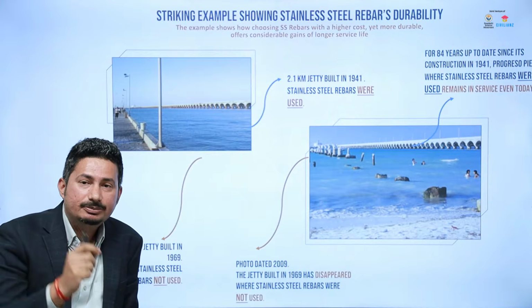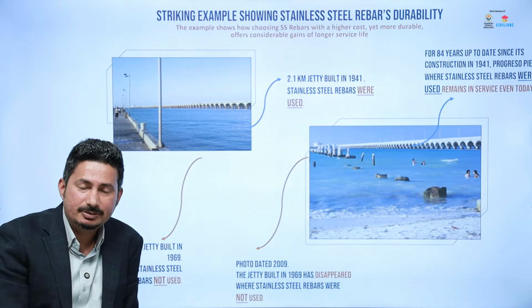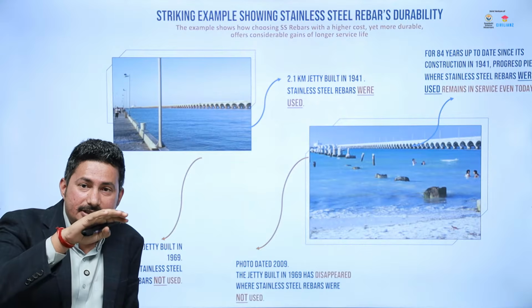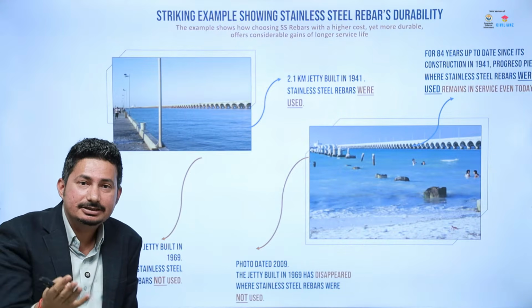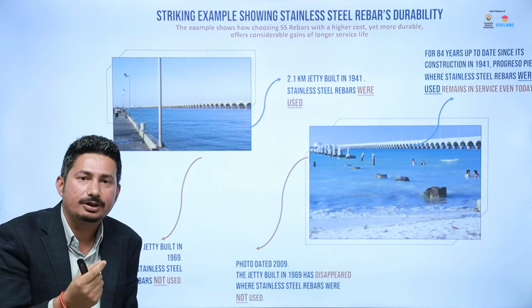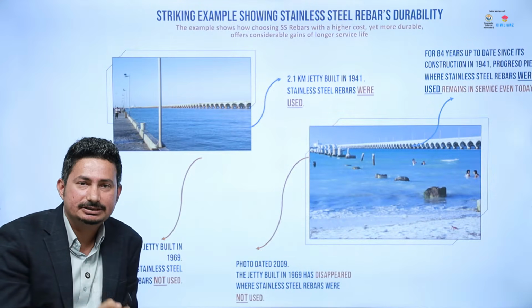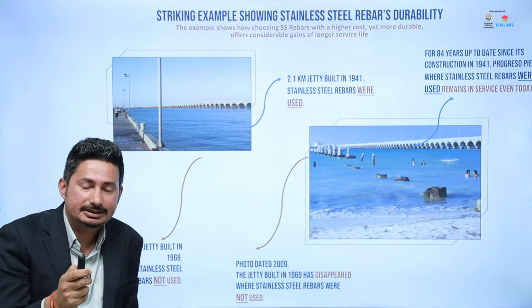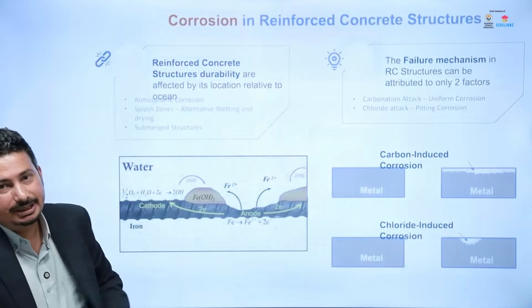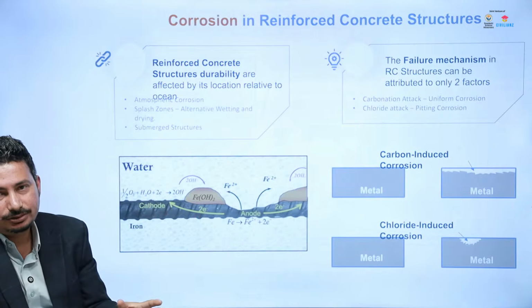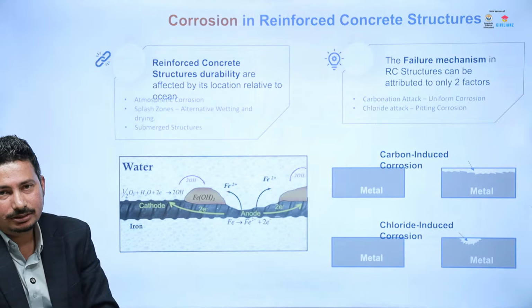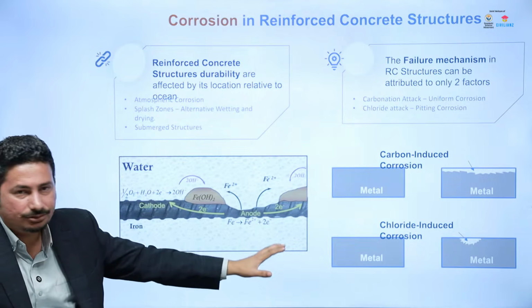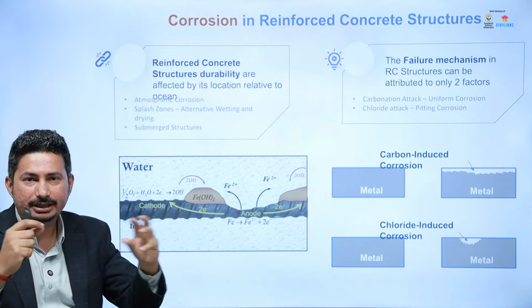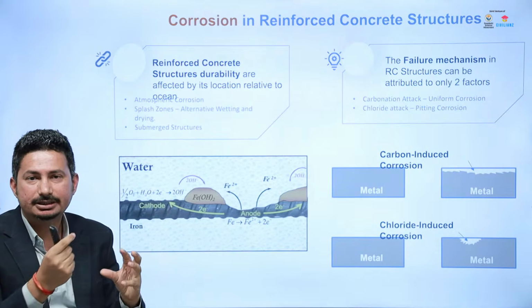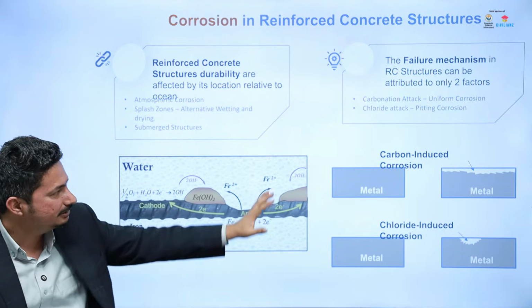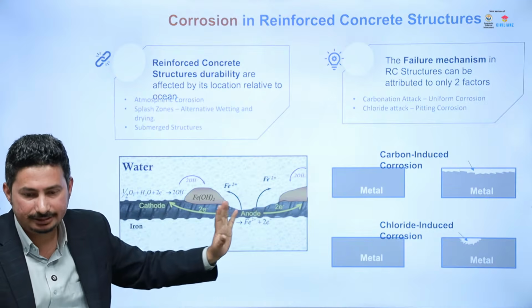Now, why did that happen? As we will see in the upcoming slide also, after corrosion of the rebar, the concrete will fall off. That action is not happening here because the rebar will not corrode. Therefore, the longevity of civil structures really increases if we use stainless steel rebars. Now, let's take the kinds of corrosion that happen on concrete: primarily carbonation-induced corrosion and chloride-induced corrosion. The anode and cathode generation will happen, and then the material loss will happen, and therefore the corrosion will happen. So primarily, these are the two types: carbonation-induced corrosion and chloride-induced corrosion.